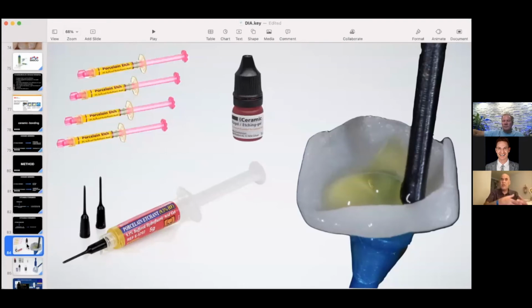So, you know, you have different etch. There are so many etches out there. You can etch lithium disilicate for 20 seconds. If you're going to etch feldspathic, different story. You have the low end etch or low concentration, and you have the higher concentration. And this is where time is going to be an issue. Low concentration on feldspathic requires between 3 to 4 minutes. If you do high concentration, 1 minute, and you'll be fine.